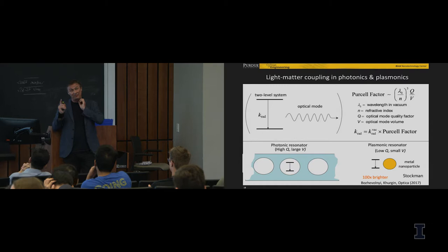It means that the response time would be fast, at terahertz rates. Typical rates at which plasmonic structures operate is terahertz. It will be broadband and fast. So basically, you get the same enhancement in light-matter coupling as you would obtain with dielectric cavities, but the system would operate much faster. And that's a simple idea.